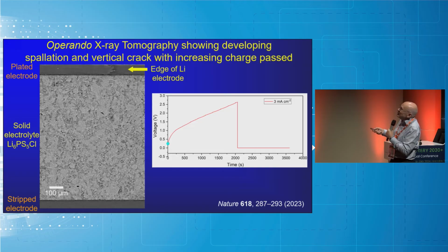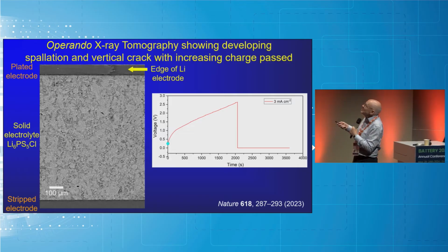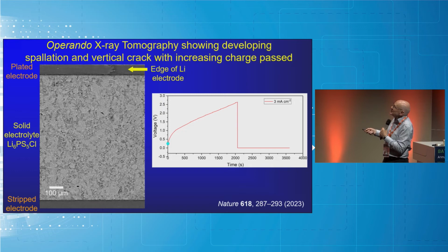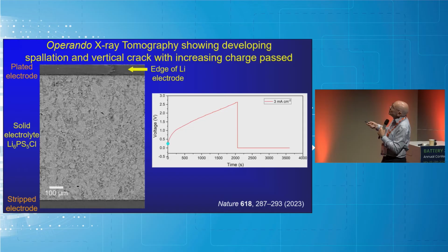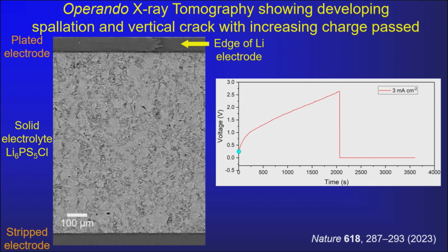So here's the argyrodite solid electrolyte. We have lithium metal on the top here. We have lithium metal on the bottom. And I'm going to run a movie here, and you're going to see the dendrite form up here and pass across the solid electrolyte. I want you at the same time to watch this. This is the voltage across this cell, this symmetric cell. And this, of course, is the point of short circuit. This is the point at which the lithium that will start here has reached the other electrode. And I want you to watch these two things, and you will see that the dendritic crack hits this other electrode before the short circuit happens. So let's do that now.